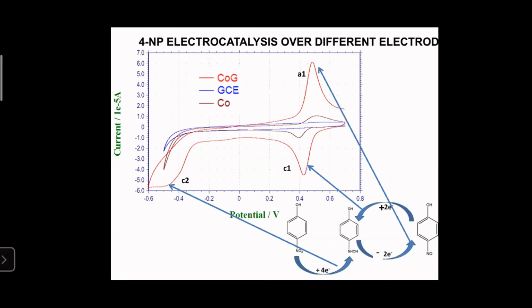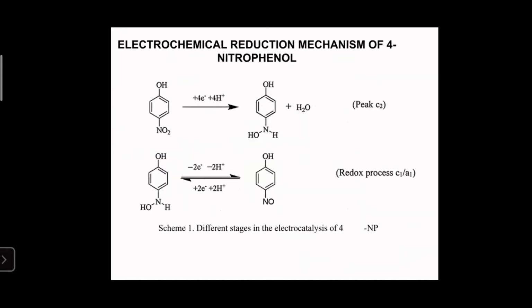Then we studied the electrocatalysis of 4-nitrophenol over glassy carbon modified electrodes. Glassy carbon was found to be inactive towards 4-nitrophenol, and cobalt modification resulted in 2 peaks in the cyclic voltammetry. But the peaks are found to be less intense, whereas the cobalt oxide graphene modified GCE shows a drastic response in CV, and the peaks correspond to the irreversible reduction of 4-nitrophenol to para-hydroxyaminophenol, and there is a redox couple of para-hydroxyaminophenol and 4-nitrosophenol. The reactions are shown here. We didn't study the electron transfer reactions now, but we have to do that also. There are 2 kinds of reactions: one is the irreversible 4-electron reduction and a 2-electron redox couple.